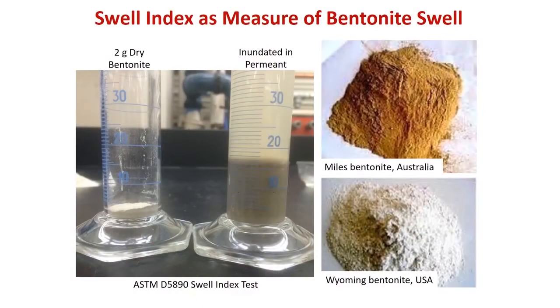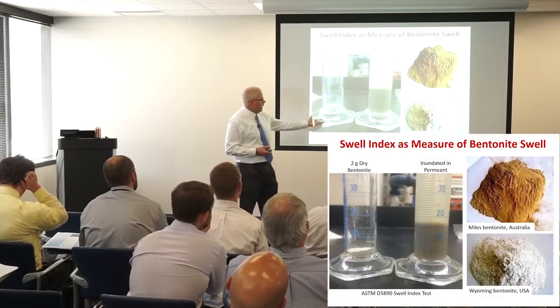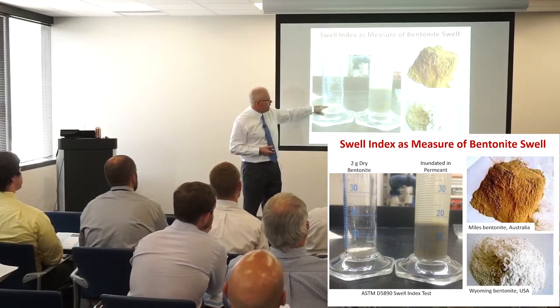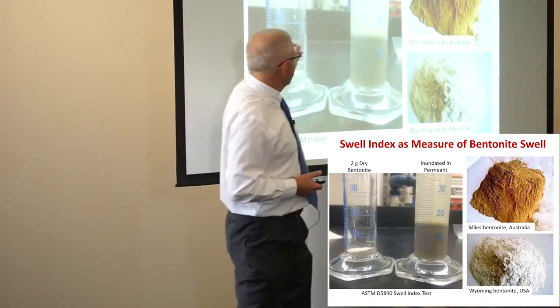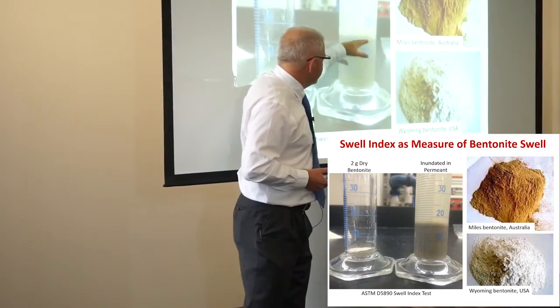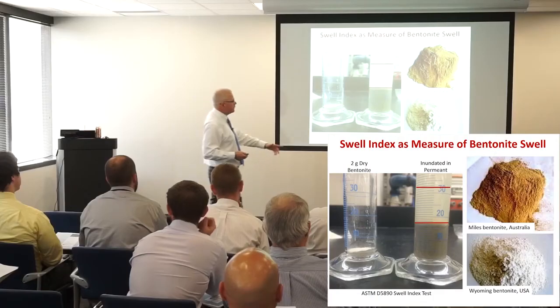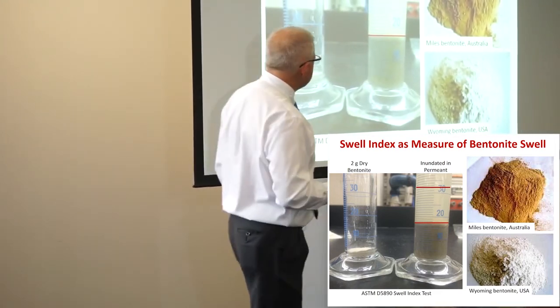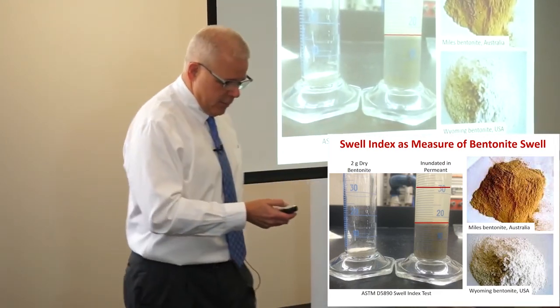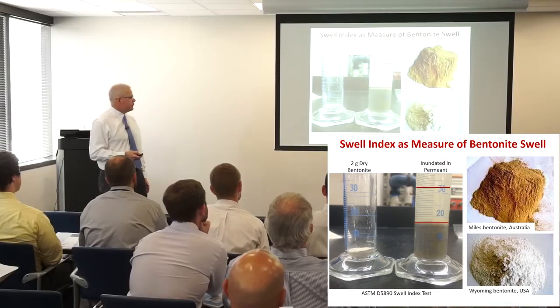In our swell test today, we use a 100-milliliter graduated cylinder. We put two grams of dry bentonite in it, then add the liquid and watch the bentonite swell. Depending on the chemistry, we'll get different readings — this one is right on the margin at about 15 milliliters. With a very dilute solution of good-quality bentonite, it would be up in the thirties. We use this test frequently to measure swell for conventional bentonites and to assess whether bentonites are compatible with a leachate of interest.